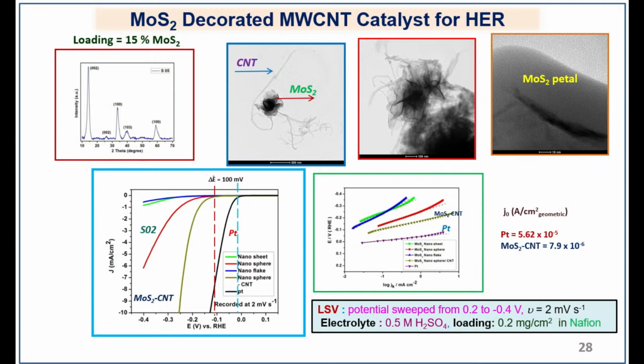Then we went to the electrochemical part, where we can compare all the other previous materials along with the MoS2 over CNT. We can see that the onset potential is now very close to platinum. The MoS2 on CNT is a little bit more active than the MoS2. Then we can see in the Tafel plot that platinum and MoS2 decorated over CNT are almost similar in the region. Then we calculated the exchange current density, the equilibrium current density. For platinum, it's 5.62 times 10 power minus 5 amperes. For MoS2 CNT, it's 7.9 times 10 power minus 6, one order lower. But I'm okay with that, because there is still room for further improvement.